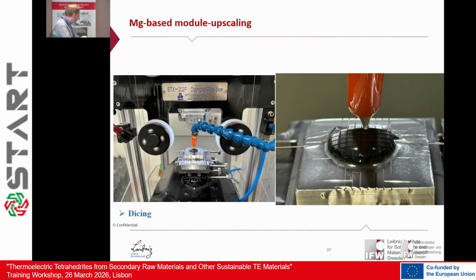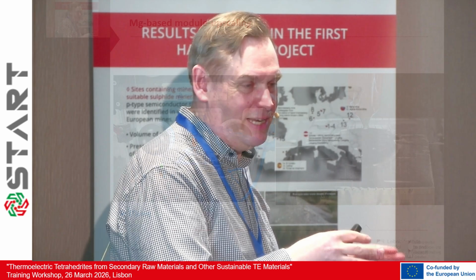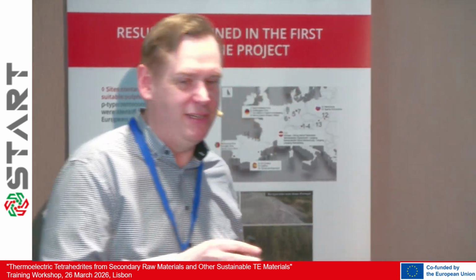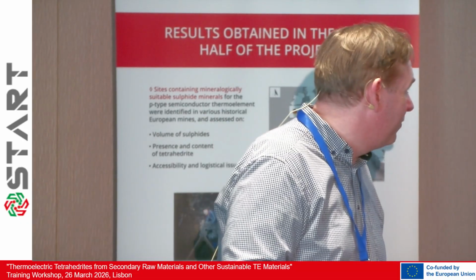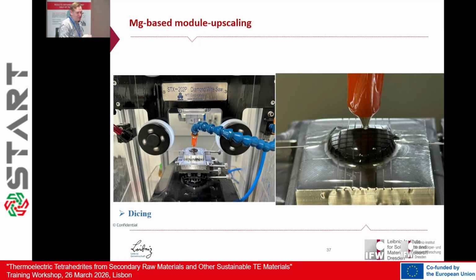What we figured out here was that the N-type material can be diced quite easily within, let's say, 1 or 2 hours. It was rather straightforward, but the P-type material was at the beginning very nasty. It took days, up to a week, to dice just the P-type material. We have now optimized the dicing process. This can now be done within hours, but in the first months this was really a bottleneck, just the dicing of the P-type material.